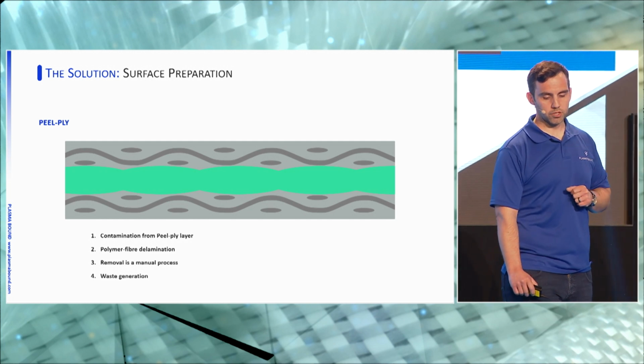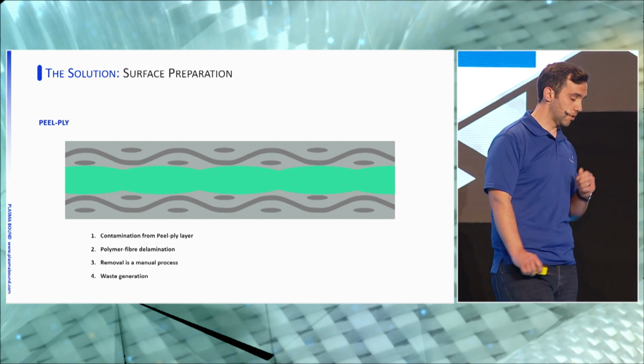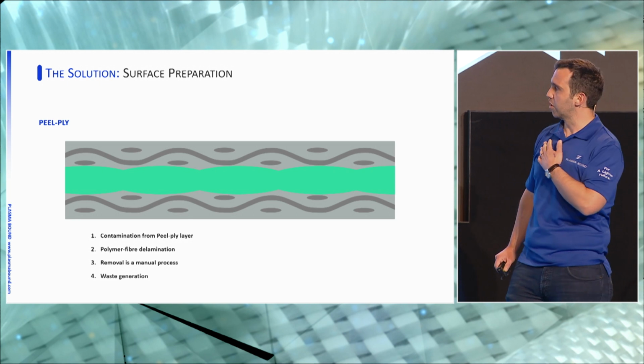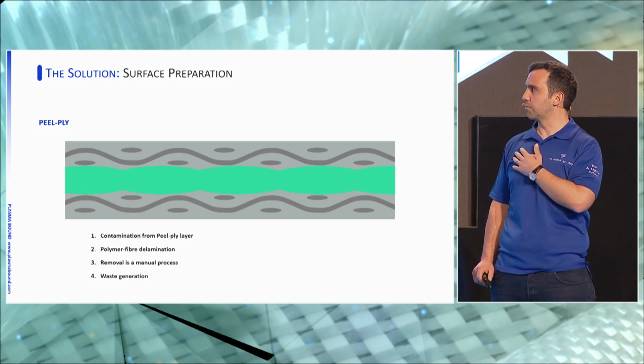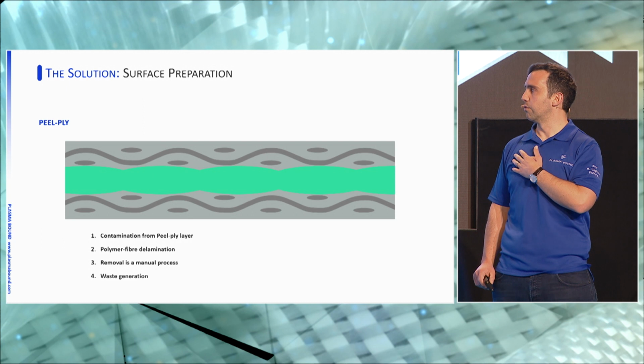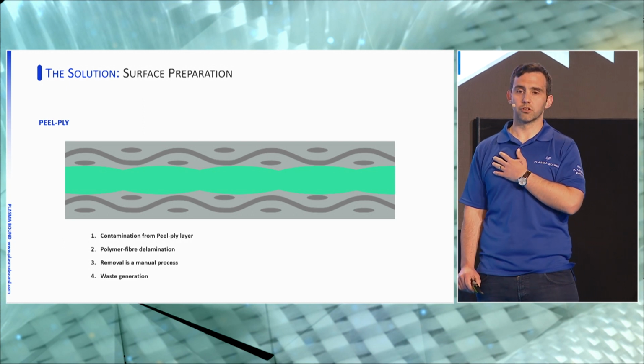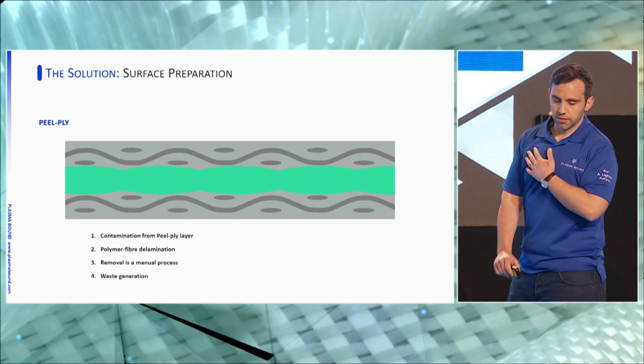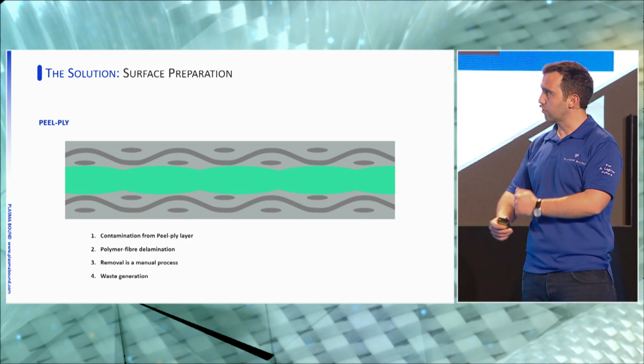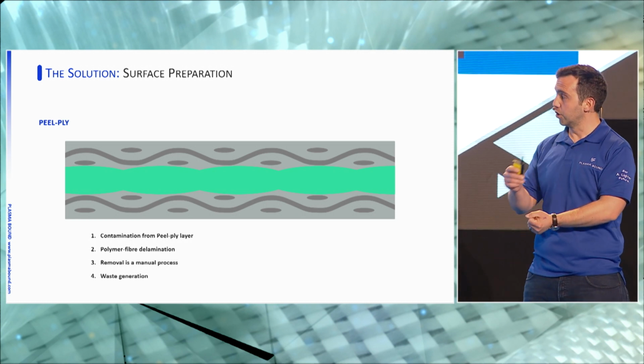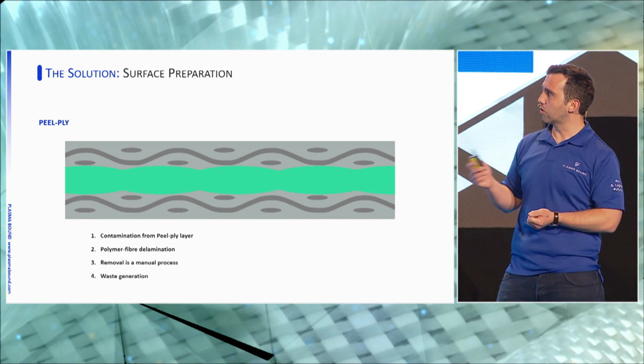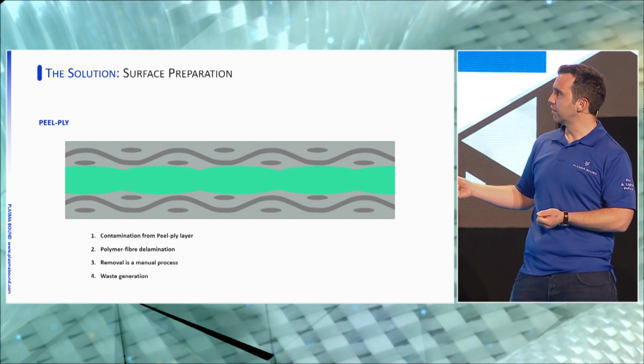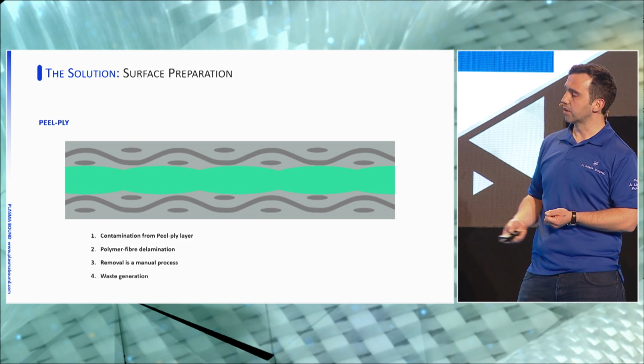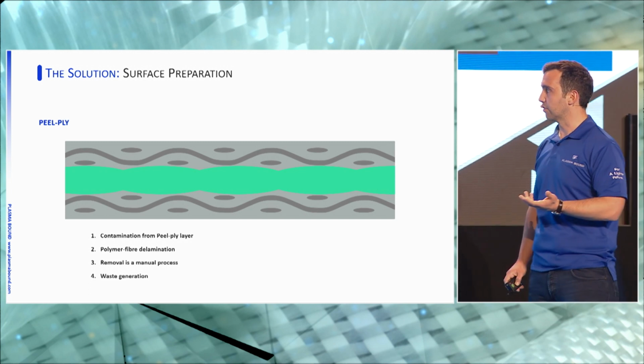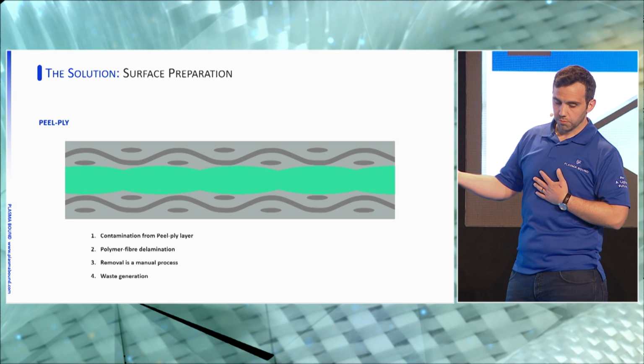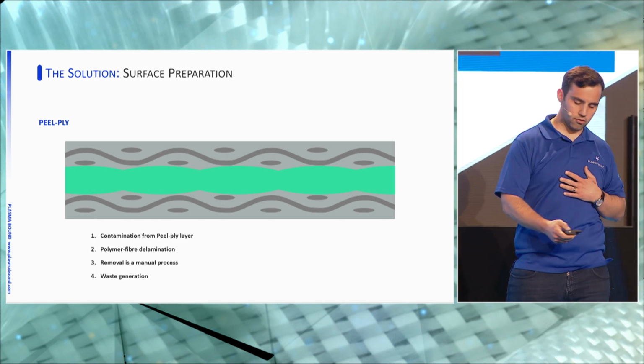And if we look at peel ply, which is very common within the automotive or aerospace industry, essentially very similar issues: contamination from a peel ply layer, particularly if you're using nylon-based. The reason being is water will be induced in. Polymer fiber delamination can occur as you're pulling it off. Depending on the human that's pulling it off and how they pull it off, they can cause delamination between this fiber and the polymer above it because of the fracture toughness of the polymer. Removal is a manual process, as already covered, and waste is generated.